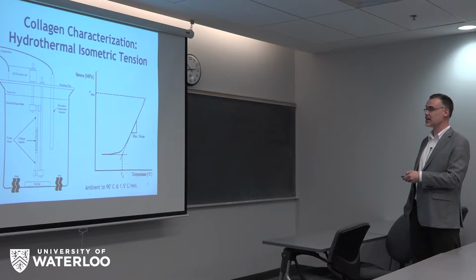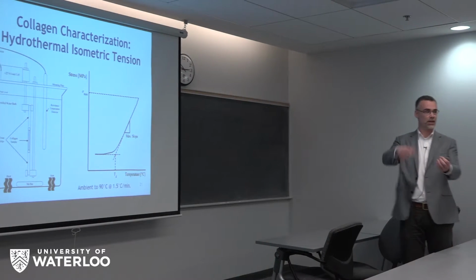But more importantly, once it's driven to melt, it's also driven to shrink. But because it's held at a fixed length, it'll actually generate a force that we can measure and convert to a stress. And we can use this slope, or the maximum slope in this range, as a measure of the connectivity of the collagen network.